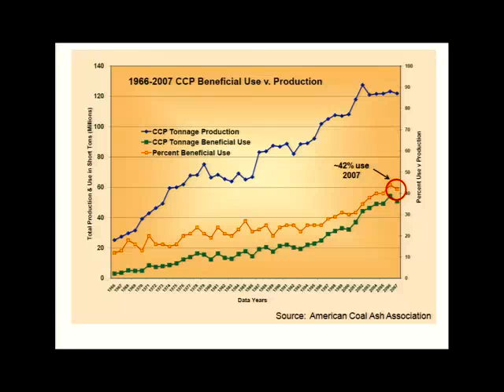So in 2007, about 42% was beneficially used in applications ranging from concrete to soil stabilization to gypsum wallboard, a lot of different applications for these coal combustion products. But what it tells you is about 58% of that material is being landfilled. Even though we're looking at percentages, if you look at the total tonnage, because the amount has gone up so significantly, we're landfilling a lot more fly ash and a lot more of these coal combustion products.